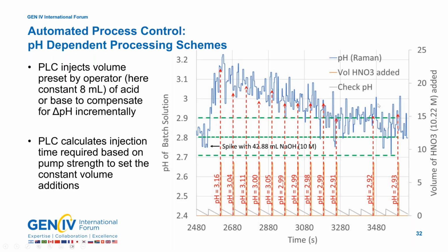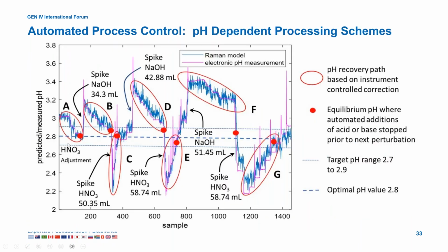I'm going to show a series of experiments where we again start outside the control zone. The PLC controller pushes the pH by delivering acid to push it down to the set point. We add hydroxide to push it out of the control zone. The PLC controller puts it back into the control zone. We add acid on purpose to put it outside the control zone. Base is delivered to bring it back into the control zone. We've done this multiple times, and we recover quite nicely.